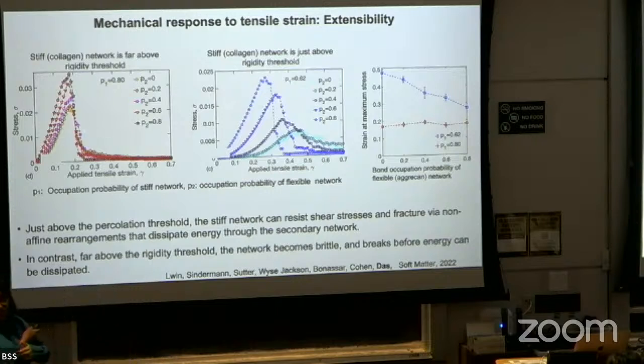So this is the thing that Anna was asking. Can I take this question after I've described this figure? So now we are looking at stress versus strain. Once again, this is a situation where the collagen is very dense. You can see that the maximum stress that the network can bear initially increases, reaches a peak, but now bonds have started breaking, so then it falls like this. And when the collagen network is very dense, these curves are all on top of each other too. There's not that much difference.